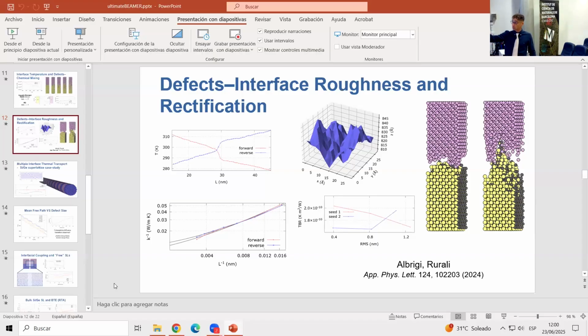And so here what we wanted to do is to sort of remove the dependence of the rectification coefficient on the thermal boundary resistance, because in practice we are interested in heterojunctions that are infinite compared to the nanoscale. So we will only see the contribution to rectification coming from the different temperature dependence of the conductivity of the two materials.